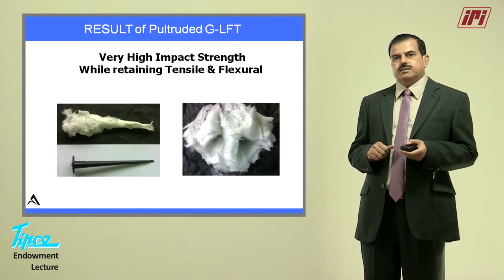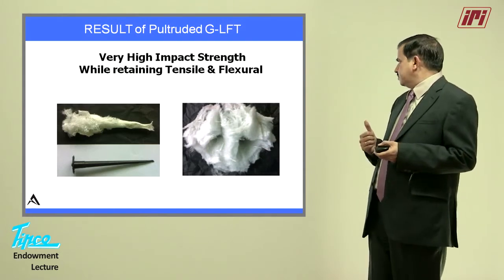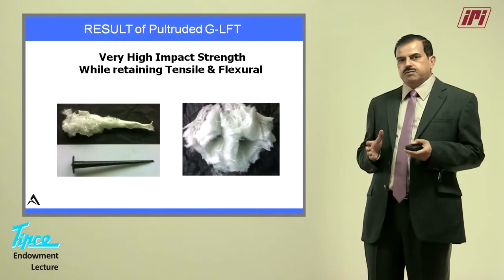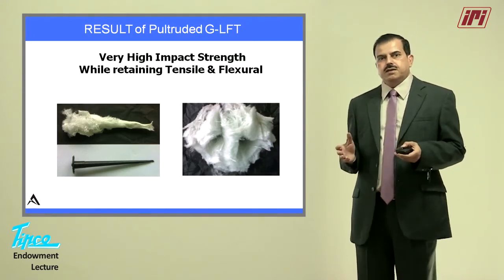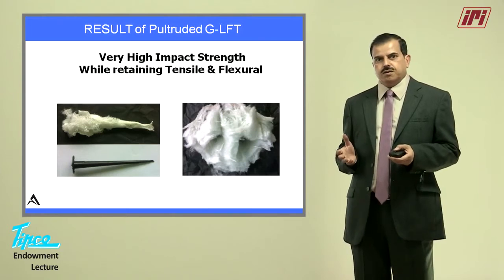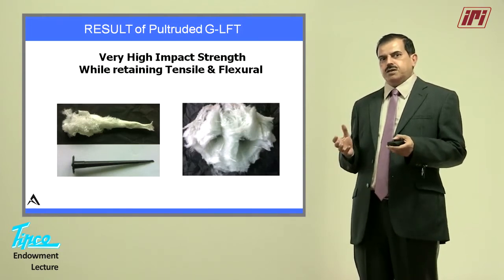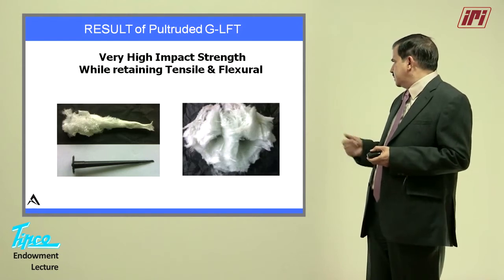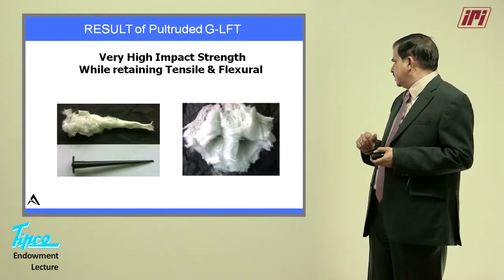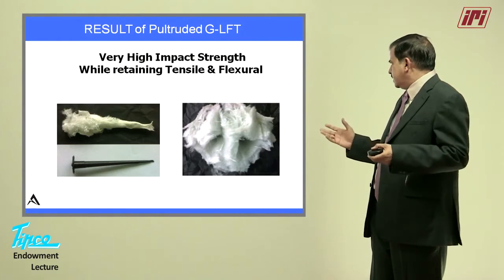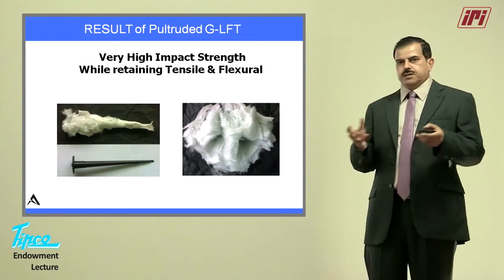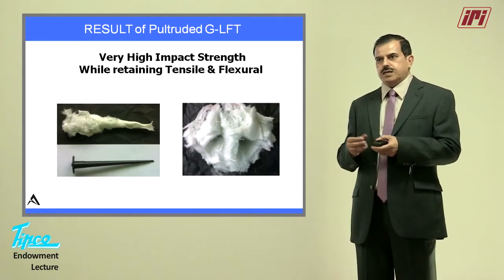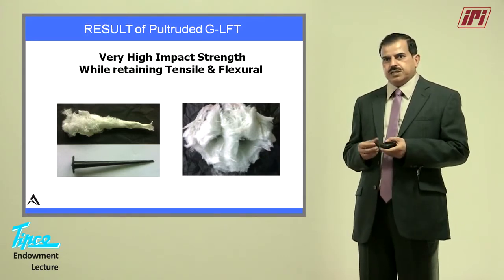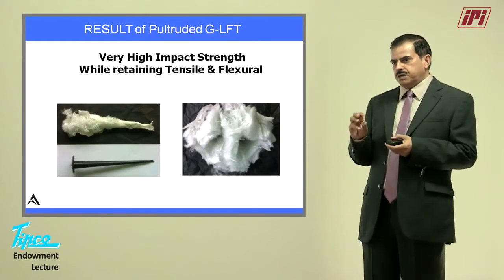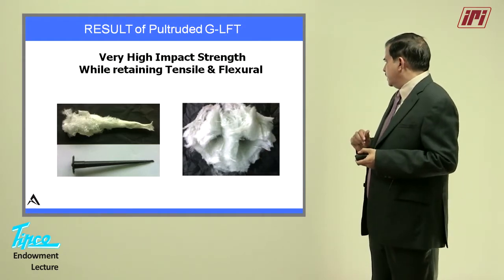Whereas in long glass fiber, what happens? You can see that whatever shape you have kept in the furnace, that shape is retained even after all the polymer has gone, all the binding strength of polymer has gone, but still you can see a structure, you can see the holes, you can see exactly how it would have been, although because the resin has gone, the fiber gets slightly expanded, so the holes become smaller than they actually were.